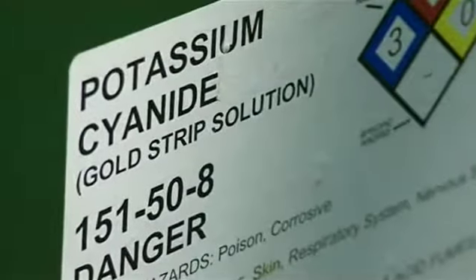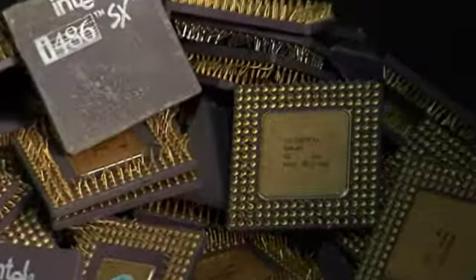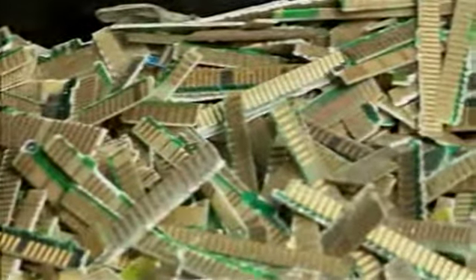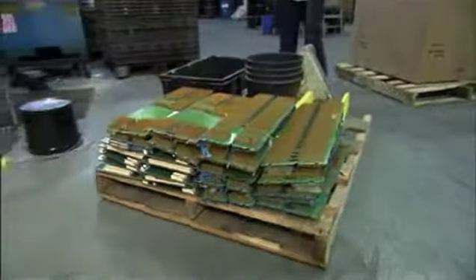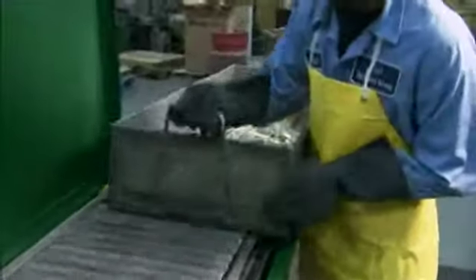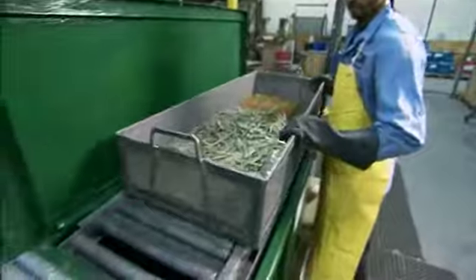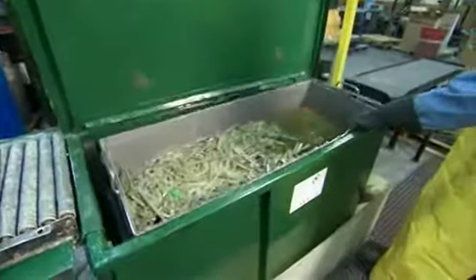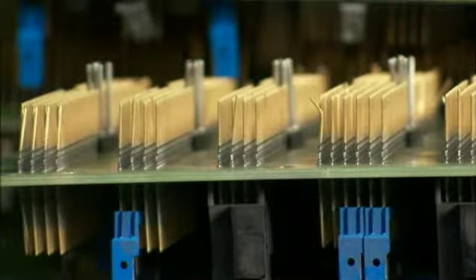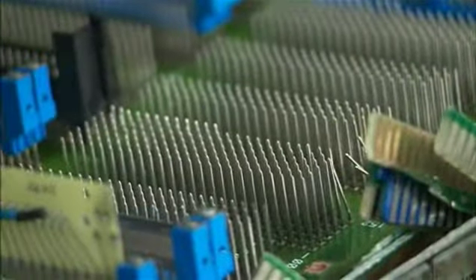They incinerate materials and pulverize in ball mills, but Colt also uses cyanide. The chemical stripping process starts with a customer's material or our own material that we've segregated. It would be put into one of 3 different processing lines that would take the material and dip it into a cyanide-based solution, which would actually strip the exposed gold off of the substrate. And the substrate could be a circuit board, it could be a connector, it could be some other type of electronic device that has exposed gold.